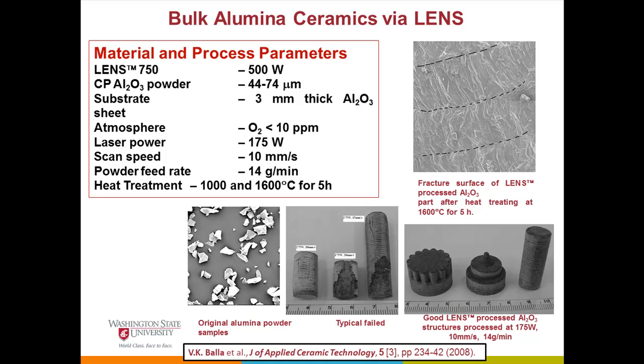Why do we need that low power? It goes back to the fundamental science that aluminum oxide is a very poor conductor and absorbs laser like crazy. We need to make sure we don't put too much laser power, or we won't build anything. So at very low laser power and scan speed, with adjusted powder feed rate, we were able to build parts.